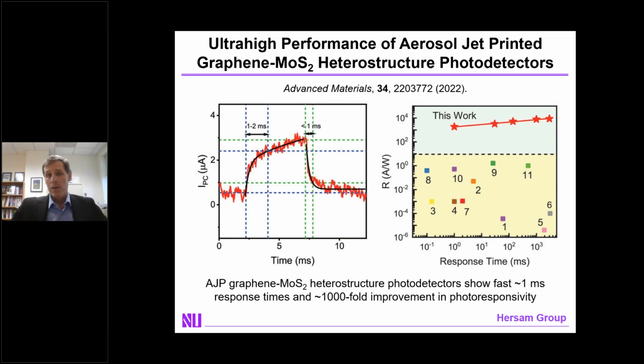And with these now optimized megasonicated molybdenum disulfide printed films, we get substantial improvement in photodetection performance. In particular, on the plot on the right, we can see responsivities that are orders of magnitude higher than what was previously demonstrated. This comes from the direct band gap character of the molybdenum disulfide. This is also done without compromising response time. Response times are now in the millisecond range, which is the best of what I showed you previously. And this is because the charge transport is effectively controlled by having these flakes going down flat in a morphology which facilitates charge transport.